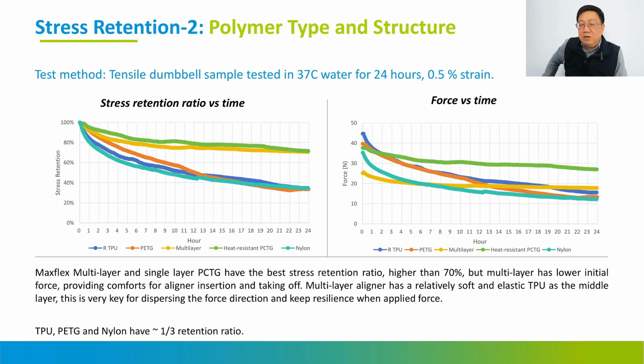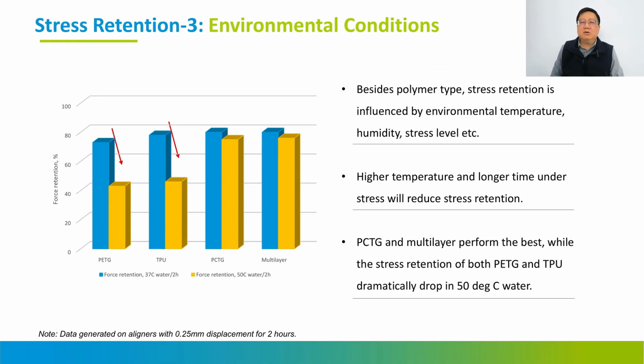It does not mean you need to have a very high initial force to make the teeth move faster. Actually, you need a more moderate force that is continuous and, if possible, has no loss. Providing the best stress retention ratio is the key to the best performance of clear aligner treatment. Of course, another thing is that if you use the material under different conditions, such as very high humidity and very high temperature, actually all the properties drop a lot.